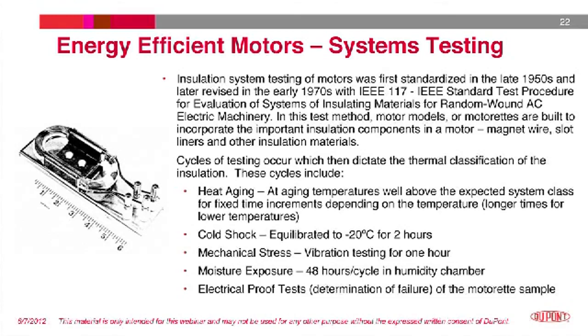Cycles of thermal aging followed by cold shock, mechanical stress, moisture exposure, and then electrical proof tests simulate motor operation, and the failure of the proof test determines the life limits of the system. For motors whose primary failure was thermal, this proved to be a useful tool and has been broadly used for 50 years.